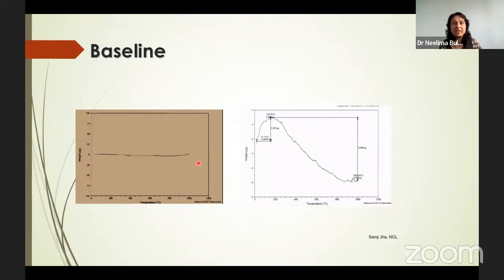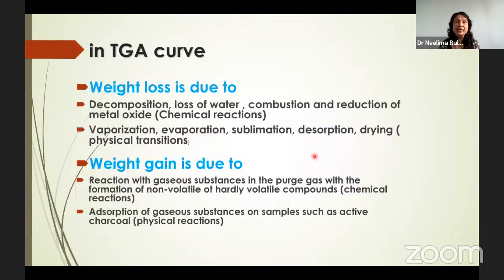And if there is a little variation in the baseline, you can see here 0.4%. Almost 0.4% variation in the baseline is only allowed to get good quality TGA data. So in TGA, many of you must have observed that you always get a weight loss, but some of you might have observed weight gain also. So let's see why you get a weight loss and when you get a weight gain.